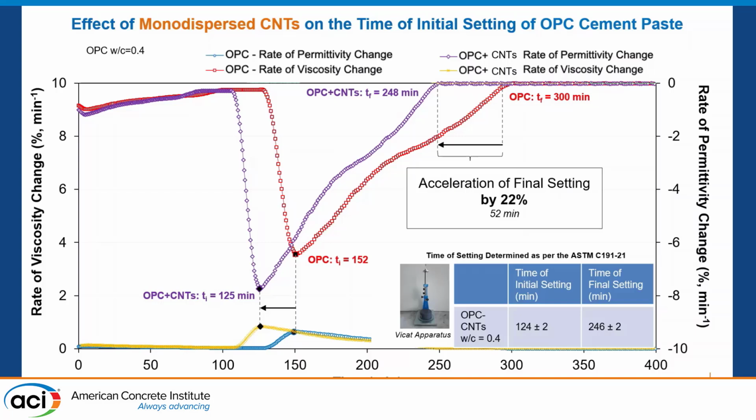And the reason is that we use a nanomaterial with an extremely high surface area. We talk about a surface area of more than 500 when the cement grains are around 130. And this is the case for the dispersed nanomaterials.